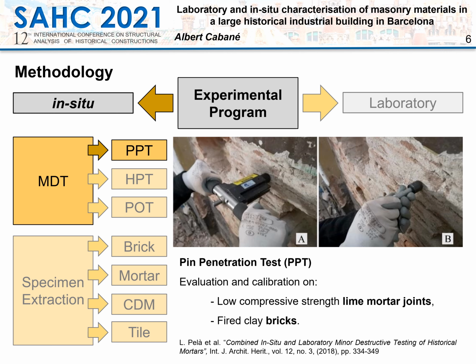The in situ experimental characterization was carried out by three different minor destructive techniques. The first one, the pin penetration test, was executed on 6 zones of masonry walls and on 4 zones of mortar plasters in order to evaluate the lime mortars and the clay bricks. The pin penetration test allows to measure the penetration of a 3 mm diameter pin fired perpendicularly using a specific device. This commercial device is commonly used on concrete and cement mortars. However, a previous research developed at UPC showed the use of this tool on low and medium strength lime mortars.